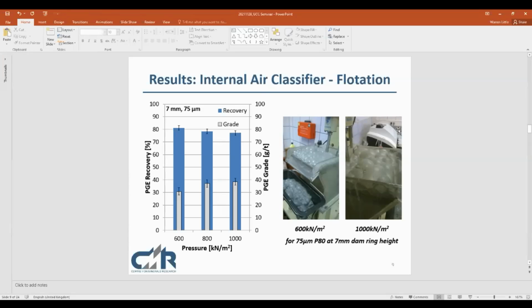The stuff at lower grinding pressure has a lot smaller bubbles, and it looks like a lot more moisture, a lot more liquid, a lot less solid loading. So what is effectively happening here is we have a very high solid loading when we are at higher grinding pressures, the same for higher dam ring heights. And this is actually destabilizing the froth and causing a reduction in solids and water recovery, which is affecting our valuable mineral recovery.